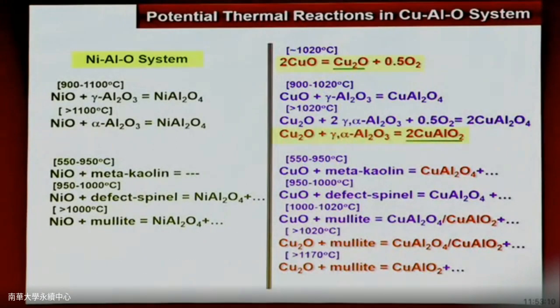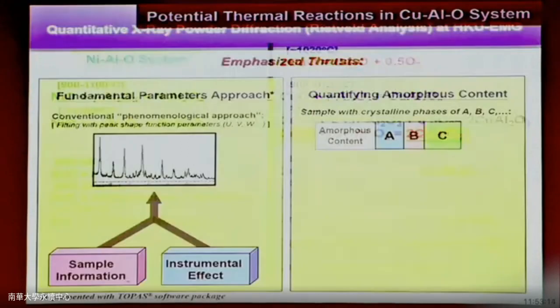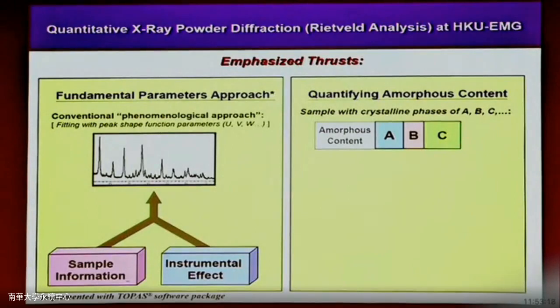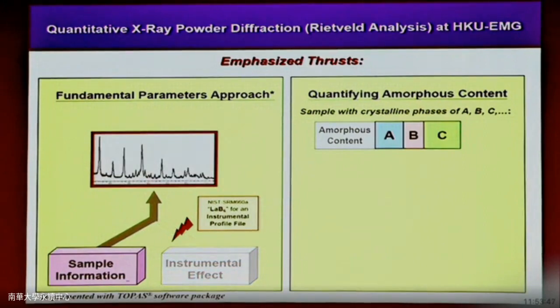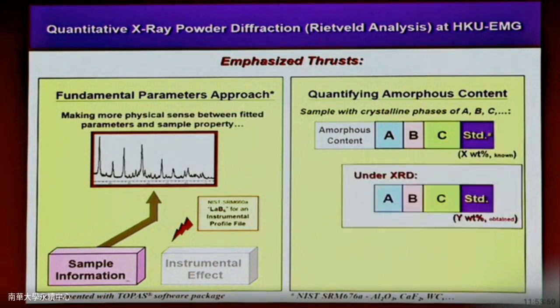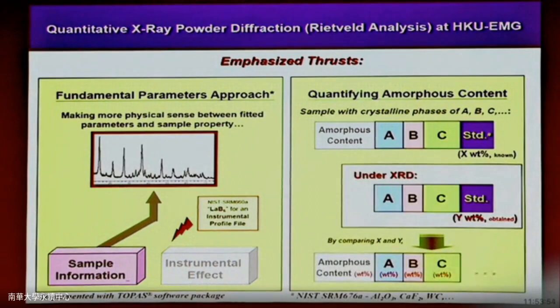I won't go too much into the chemistry, but I'm trying to say we look at nickel, we look at copper, we look at all different kinds of metals. And one of the good things that we have in the lab, which is quite unique in the world, is that we use a fundamental parameter approach that makes the spectrum analysis more meaningful. Because at this moment, a lot of labs have their sample results basically mixed with the sample information together with the instruments. So you have to really have what we call a fundamental parameter approach to get rid of that instrument effect and generate the new phases coming out and do a more physically meaningful analysis on that. We also have to use the internal standard to really find out the amorphous content because XRD is not able to see amorphous content. You have to have the internal standard. Otherwise, a lot of research without internal standards, actually, I think the data is not reliable.